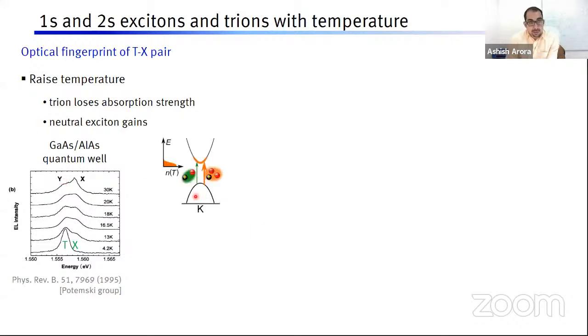To understand why this happens is the following. For creation of a trion, we need excess electrons. So we need a doped semiconductor, right? So we have this valence band and a conduction band, and then there are some excess carriers which are represented by this orange line in this band diagram. Now, for creation of a trion, you need extra carriers here in the center of the band where the optical transition takes place. So if we are at low temperatures, we have some Fermi-Dirac distribution of these carriers, and many carriers are available for creation of trions. So you can easily create many trions.